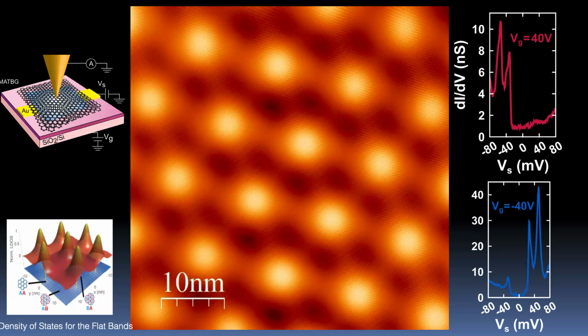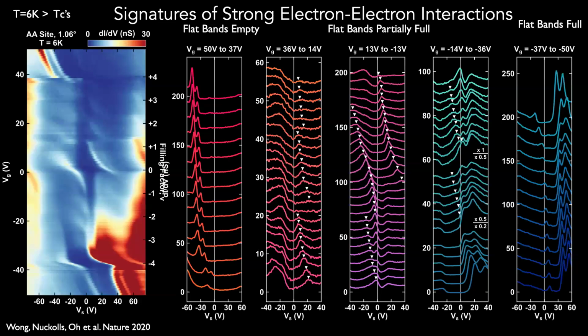And what is interesting, the first thing we discovered in this field, is what happens as you start to partially fill these bands: all the spectral properties of the flat bands become extremely broad. So this plot is supposed to be read like this. It goes down, back up, and down, back up. You can see that there are these two sharp peaks, and the sharp peaks are being tuned to the chemical potential by the gate voltage. And then as you reach the chemical potential, they become extremely broad. Then they get a little sharper around charge neutrality, and then broad again. And then when they exit the region near the Fermi energy, they become completely unoccupied, and they become sharper.